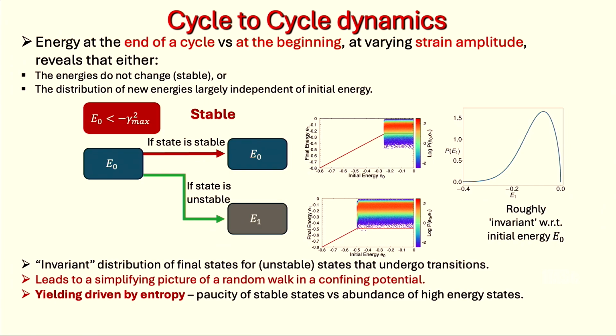But at this stage, I'm going to take this already simple-minded model and make it even simpler. Instead of looking at transitions from one mesostate to the other, as I vary the strain cyclically, I'm going to ask what might happen to the system if I look at it at the end of each cycle, stroboscopically. And here are some simulation results for this system where I'm showing the initial energy of the mesostate that I'm occupying on the x-axis, and the final energy after a full cycle on the y-axis. Without going into the details, what you can see from the color map is that the final state that I reach at the end of the cycle doesn't seem to depend much on where I started.